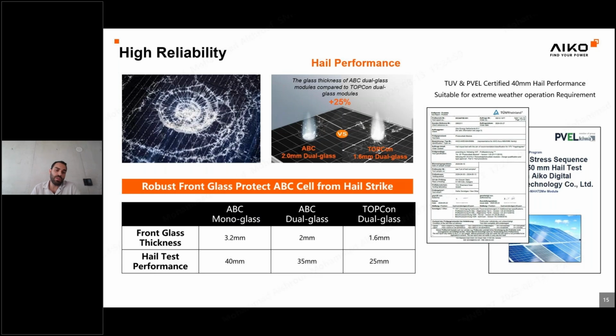So for the monoglass panels, we use a 3.2 millimeters glass thickness, and normally we have passed the 40 millimeters hail test performance. And for the double glass panels, we use 2 millimeters glass thickness, and we have passed the 35 millimeters hail test performance. I would say the majority of the TOPCon double glass panels in the market nowadays use 1.6 millimeters, and this is a downgrade for the hail resistance, and also in terms of mechanical load. So this is also another advantage we have in our panels.